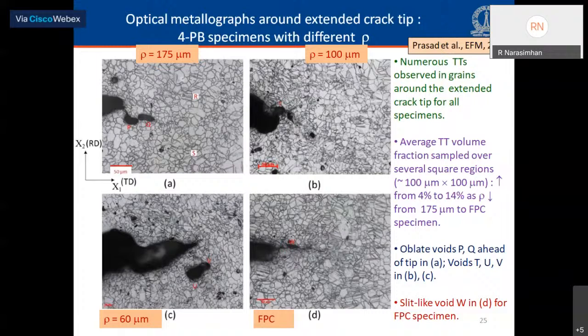Now, taking a look at this FPC specimen, if you closely observe ahead of the crack tip, there is a slit-like void, which we have labeled as W, and this is presumably associated with the twin-induced crack that has formed. On the other hand, if you examine all the other optical images pertaining to the pre-notch specimens, you would notice that there are some oblate voids. For example, if you look at the top left image corresponding to the 175 micron notch root radius, you'll see two voids P and Q, which have actually coalesced with each other, and they're about to coalesce with the tip as well.